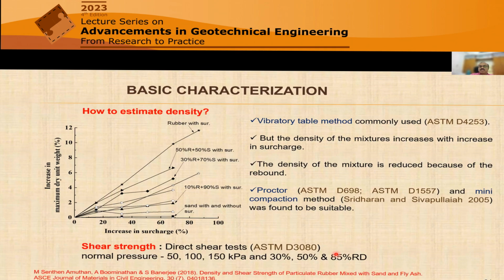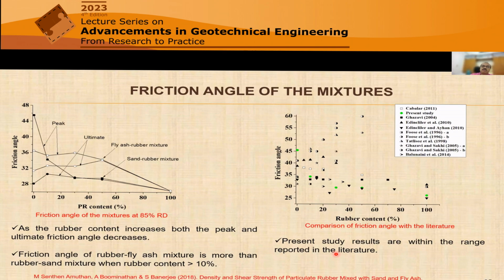Now we did the direct shear test as usual for the cohesionless material. The direct shear test result shows a very interesting thing. In fact, we compared the friction angle obtained by us as well as by others all together in this particular plot, and the green points are ours. One of the things we first noticed, which is expected, is that as the rubber content increases, the friction angle is reducing. Obviously, if you have pure sand, your friction angle is definitely high. With rubber, you are reducing the friction among the particles, so you end up having a low friction angle. So that is a positive as well as a negative. We'll see when it is positive, when it is negative.